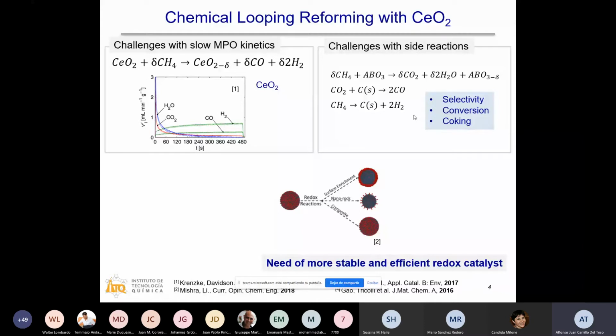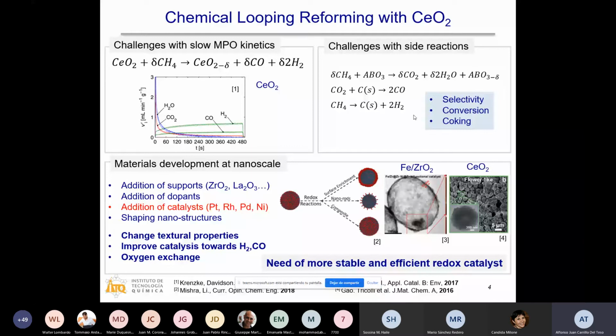But if you dig in the literature, there are many others, such as additional support like zirconium oxide, shaping into nanostructures like this beautiful flower-like cerium oxide, addition of dopants, we have done a lot with cerium oxide, or addition of metallic catalysts, these ones that will be the point of my talk. And by all these changes in our materials, we can change textural properties or thermodynamics, and this will improve the catalysis toward higher selectivities or conversions of methane, which is what we are looking for.